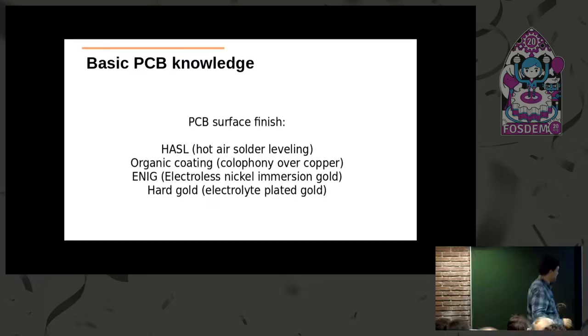What options do you have for the PCB surface finish? The classic is hot air solder leveling. What is this? It means the PCB when produced is with copper layers. Copper is good for soldering, but it oxidizes very fast. So there must be some protection, a coating above the copper. And with hot air solder leveling, the PCB is dipped in melted tin, and then when it is taken off, hot air blowers remove the excess solder from the surface of the PCB. It's not very even. So you can use it for the plated through-hole components, but if you have BGAs or QFNs, they might not lie on the PCB perfectly, so you might have voids in the soldering.